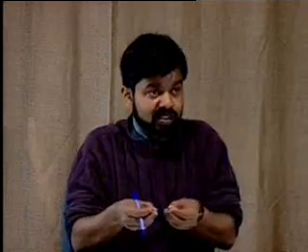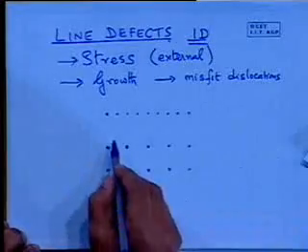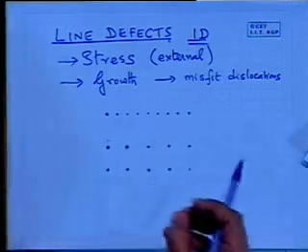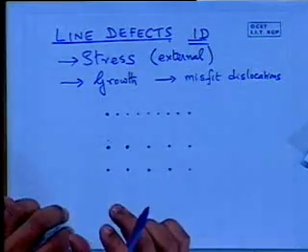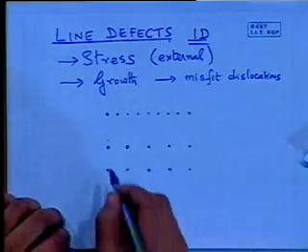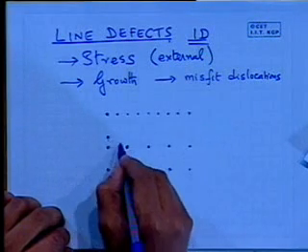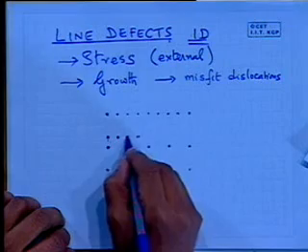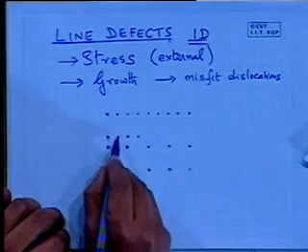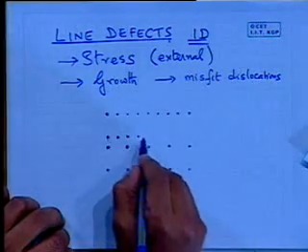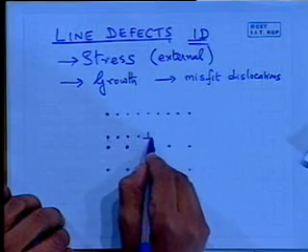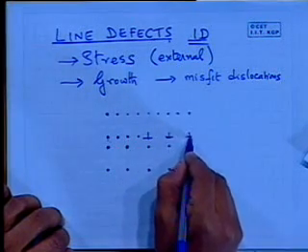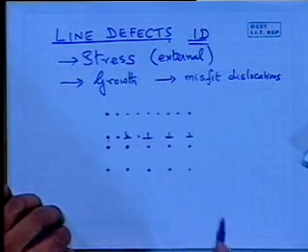be stressed. And as a consequence of that, the atoms will sit more or less accommodating the substrate. But beyond a thickness, that stress will be so high that eventually this will start sitting at its own spacing, this far apart. Periodically, to account for this change in lattice, it will introduce some kind of a dislocation. Very regularly, it will introduce a dislocation.